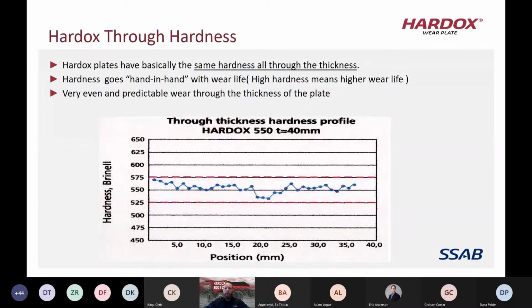And this is a chart showing Hardox 550 at 40 millimeters. If you go across the chart from left to right, at the 20 millimeter mark, the center of the plate, we see our lowest measurement, but it's still not below 525, which is the minimum hardness for Hardox 550. This is really important whenever you have large or thicker plates that are wearing. As you get closer to the center of the plate, with some competitors you could drop 100 Brinell points, and then you're going to wear much quicker at the center of the plate than at the surface.